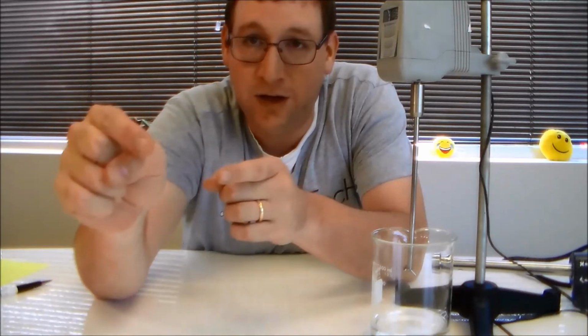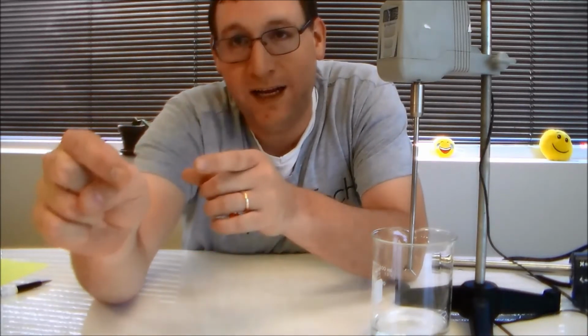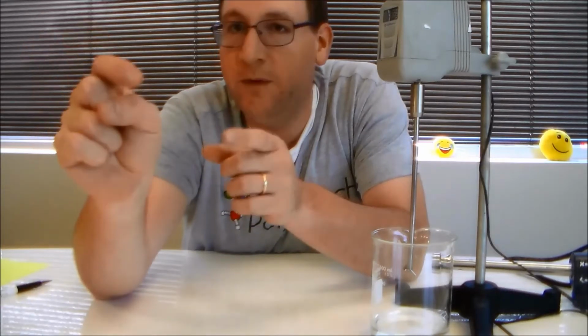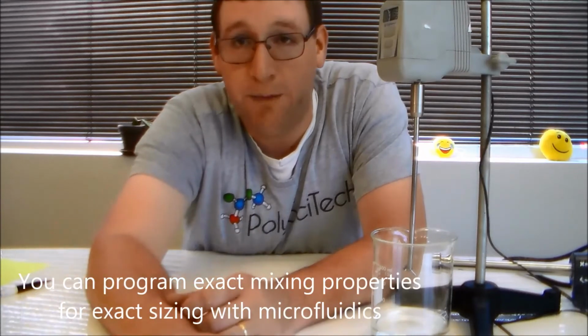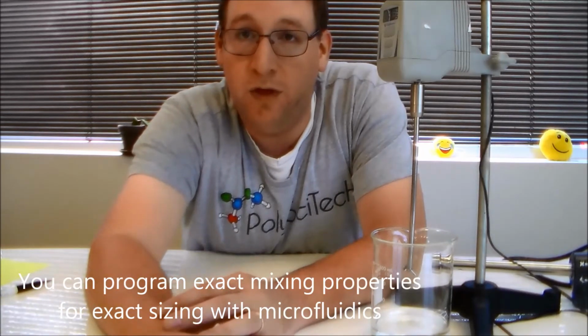There are similar methodologies that have been developed recently using microfluidics, which essentially performs this kind of action. However, it performs it inside of tiny little channels where the water and the organic solvent are mixed together at very well-known rates, very well-known amounts. And in this mechanism, the nanoparticles and microparticles have a very uniform size and very uniform properties. So that's what's used typically for making those.